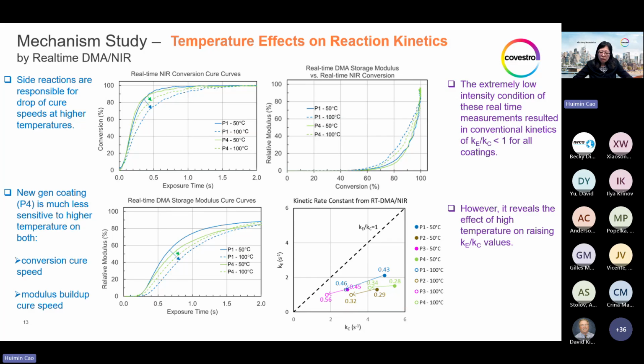And this means less drop of Ke than Kc at higher temperature. And this is an indication that the fiber drawing process, where the fiber temperature during curing can be as high as 100 degrees C or even more, is likely to have a higher Ke over Kc ratio, and that maybe makes it possible for reaching or exceeding 1.